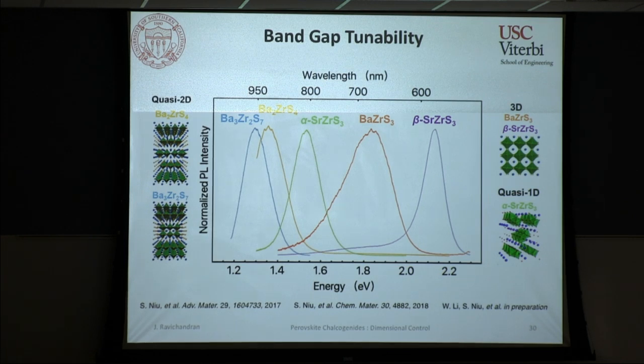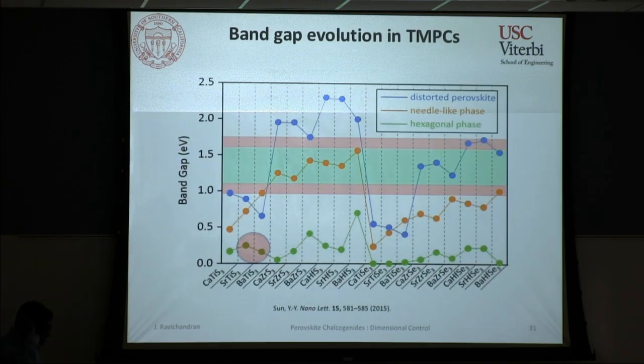I don't want to keep you for very long, but I'll try to go through the last bit fairly quickly. The other thing that really got our interest was this corner of this prediction graph from Professor Shengbai Zhang's group at RPI. There was a prediction that if you can crystallize hexagonal phases for these titanium-based compounds, you can get band gaps fairly close to the long wave infrared or mid-infrared range. This is very interesting because, as I mentioned earlier in my talk, communication and sensing in the infrared remains an important bottleneck, and that's something these materials could address.